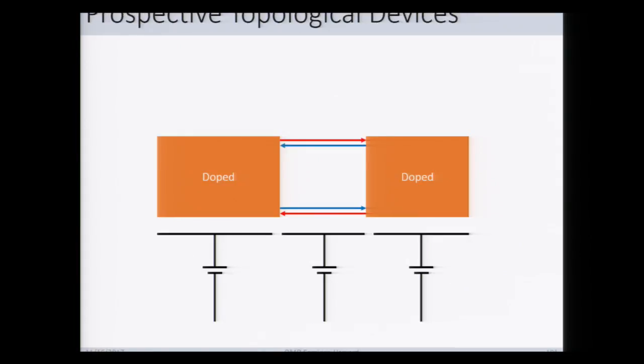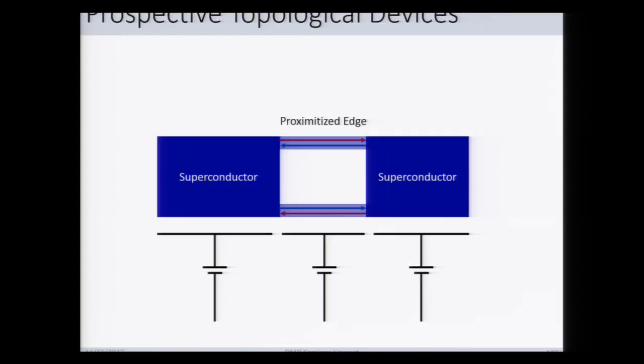Yeah. So recall that this is exactly the geometry of that first experiment. We dope everywhere in the sample into the conduction band of the same material, and one local region back undoped into the insulating state by local gate potentials. And this apparently makes pretty good contact, and in this case, metallic contact for now. And if you cool it more, the contact will become superconducting. That's right. That's the concept, and hopefully the transparency is as good as it seems in the metallic phase to give us a nice proximity effect.